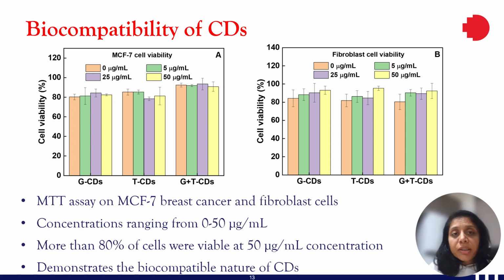We further studied the cytocompatibility of these materials, and the influence of carbon dots on MCF7 human breast cancer cell and fibroblast cell toxicity was studied using MTT assay. And the cytotoxicity measurements were made with different concentrations of carbon dots ranging from 0 to 50 microgram per ml. The average cell viability remained above 80% for the highest tested concentration, demonstrating the biocompatible nature of these carbon dots.